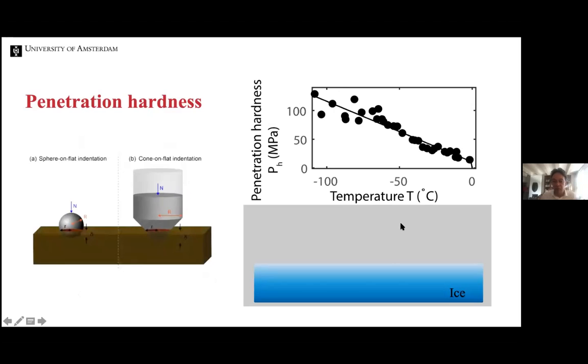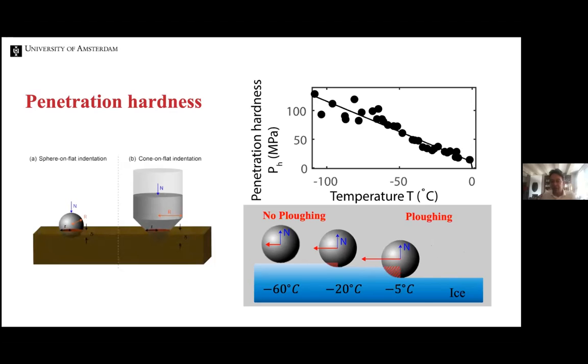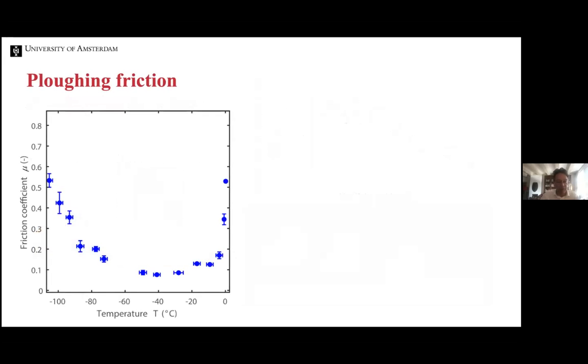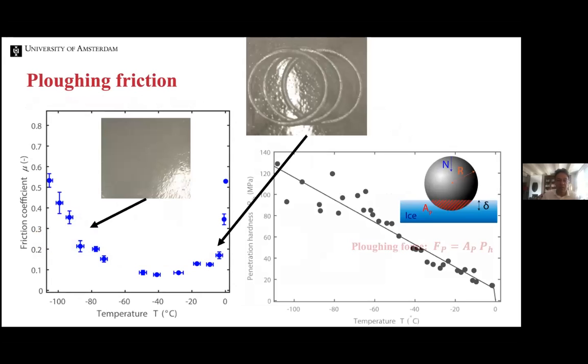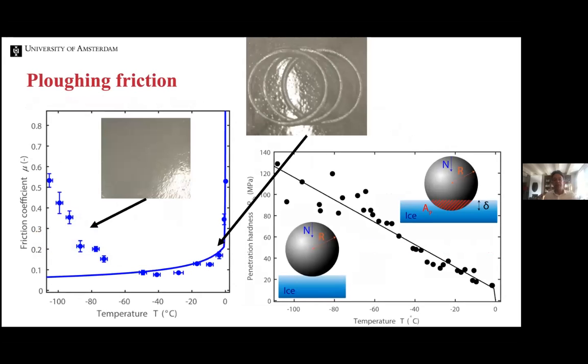And so what happens is that if you are at -60, the sphere simply slides over the ice because it has not a large enough force to plow through the ice. At -20, you start plowing, and at -5, you really leave a considerable trace on the ice, in the ice, I should actually say. And so that is what we also saw in the experiment. And you can now make that quantitative with the calculation and the measurements, and then you get the blue curve, which quantitatively describes the behavior very close to melting. So far, so good.